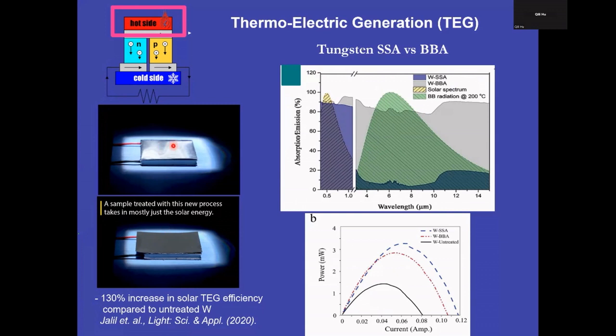It scatters everywhere. It's hard to see. When the black metal is here, you can clearly see it. It's very bright solar light shining upon it. And we got immediately a 130% increase just by putting the black metal on the hot side, okay?